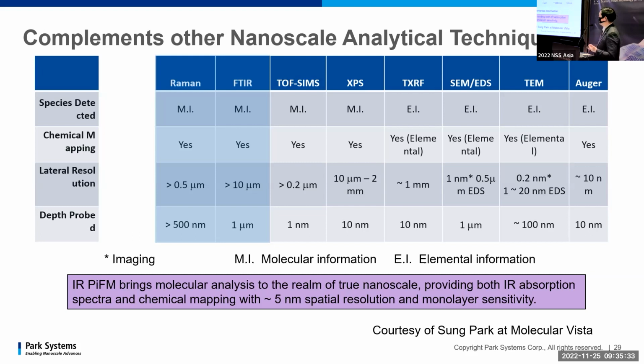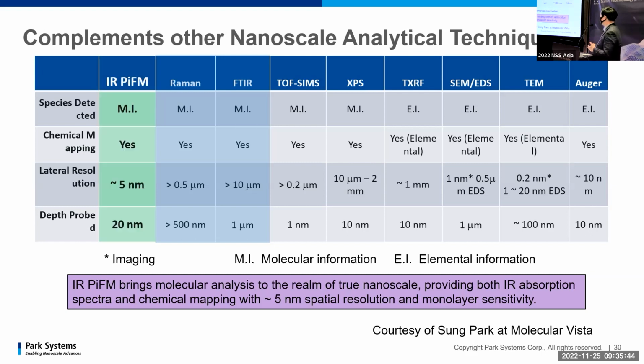One is the Raman technology, but the problem with Raman is that the signal is too weak, and also there are a lot of other operational difficulties. But with PIFM we can do molecular analysis at nanoscale, both the IR absorption spectra, as well as mapping the chemicals on the surface in less than 5 nanometer range.